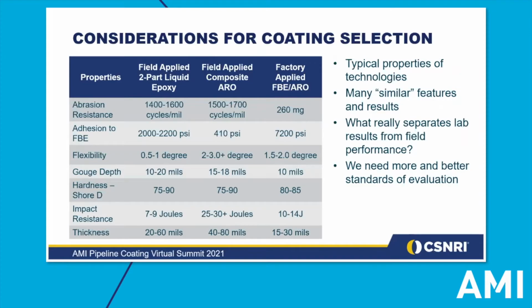When using a liquid epoxy or field joint coating, the standard recommendation is to increase the thickness, which can increase the brittleness, thereby increasing the probability for shear disbondment when bending load is applied. We also see hardness values, and while some see this as a higher number equals a better number, hardness is really only an indication of the cure of that specific material.